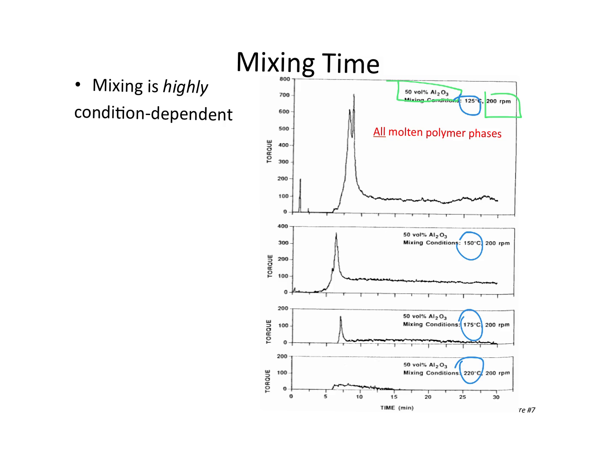Why is there, well, first off, let's start from the beginning. This is time on the x-axis, we start mixing and mixing, and at some point, we have a very high torque excursion, let's call it that. And so the torque on the system suddenly increases. And what that means is the alumina and the polymers are all going into this mixing cage, and it has to work really hard to tear down agglomerates. And that's what's happening here, agglomerate destruction and mixing as well. Okay. So everything gets sucked into it, and now it has to work really hard because it's dealing with this polymer and these ceramics.